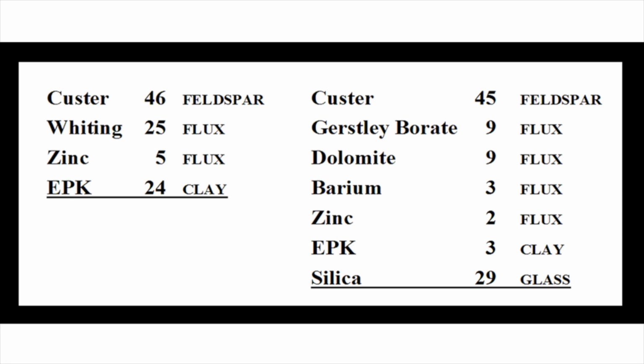Again, the bulk of the glaze content in both glazes is the feldspar. Secondly, one of the glazes contains a strong, low-melting flux, Gerstly borate. Thirdly, one glaze has no extra silica in it. Fourth, one of the glazes is very high in silica with a very low clay content. Therefore, you can conclude the glaze on the left is a matte glaze and the glaze on the right is a glossy glaze.